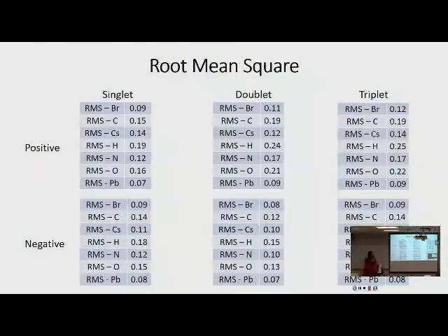So, where was I? Okay, root mean square, and this is just a bunch of tables of the calculations. I decided to do the root mean square for each atomic element, because since it's normalized for number, if you did them all together it would wash out any meaningful data. The ones I'm going to focus on mostly are bromine, lead, and cesium. For the positive polarons anyway, there's a consistent trend where with increasing spin multiplicity there's more deviation of the bromine bond. You could correlate that to the positive charge and the bromine being negative: with increased multiplicity, they contract inward a little bit more. That's one hypothesis anyway.